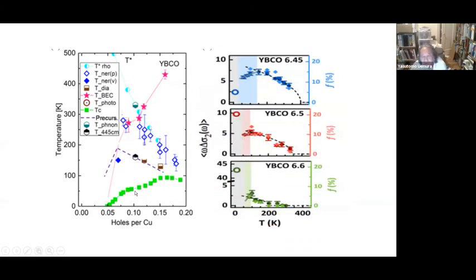Okay. Now, Andrea's experiment was published on YBCO at different concentrations. Essentially, he is able to measure this transient superfluid density in various YBCO systems. And this circle is the equilibrium superfluid density. So for the case of 6.6, the superfluid density onset temperature is something like 150 or 200, and the superfluid density is small. Anyway, this onset gives a point here. For this 6.5, the superfluid density is somehow similar to the equilibrium value, so we can actually plot it with the μSR superfluid density. The onset temperature is something like 300 or 350, and it gives, therefore, the point here. And this point could be interpreted in both ways.